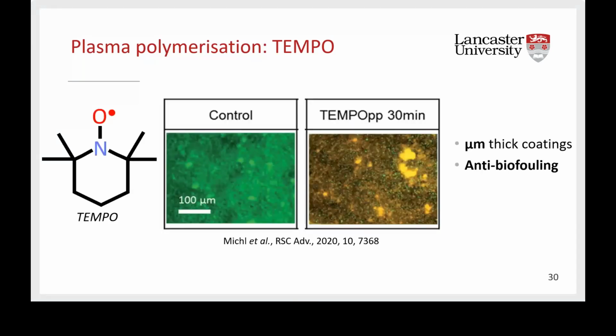And actually, in literature, you can find evidence of TEMPO plasma polymerization. In the control figure, you can see a silicon wafer being completely colonized by bacteria, and bacteria adhering to a surface are highlighted in this green color. Then in the next figure, you can see a silicon wafer being coated by a TEMPO plasma polymer, and again tested for bacterial adhesion. Now you can see only tiny green spots, meaning that very few bacteria are adhering to the surface. Most of them are highlighted by this orange-yellow color, meaning that they are not attached to the surface. So actually, TEMPO exhibits anti-biofouling activity when it is several micrometers thick.